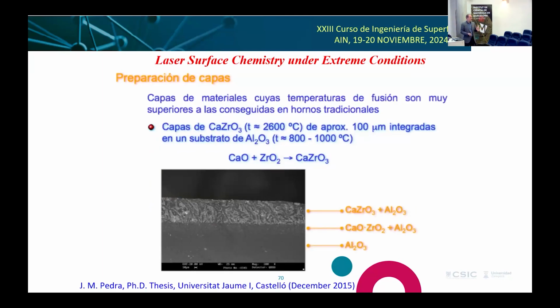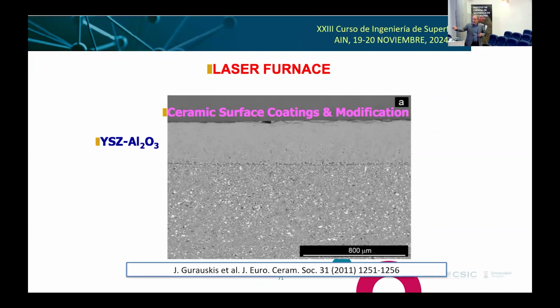You can mix calcium oxide and zirconium oxide and get calcium zirconate, which melts at 2,600 degrees. In situ. In this case, because the substrate is alumina, the alumina flows up because it melts at lower temperature, and you get a composite. But it's a very nice composite. It's completely integrated at the atomic level. You can see here, this is a eutectic of yttrium stabilized zirconia, which also melts well above 2,000 over what we call a porcelainic ceramic. Very nice. These are all published.